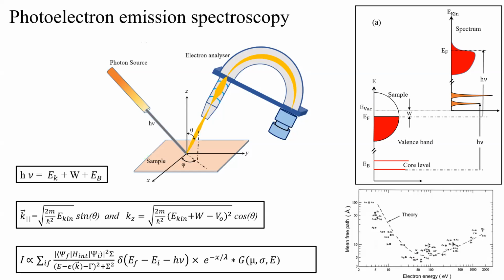I can give you an example. If you have sodium metal, you have the sodium 3s orbital outside and all the core states: 1s, 2s, 2p. These core level states are isolated in the sense that they are very far from the next neighboring atom, so their wave functions cannot overlap with the neighboring atom's wave functions. So there will be no hybridization between the core levels of one atom and the core levels of another atom. That's why you will always get an intense, Dirac delta type of feature for the core levels.